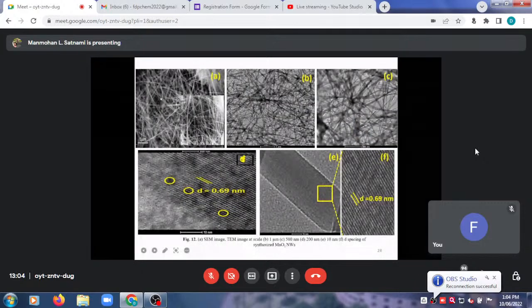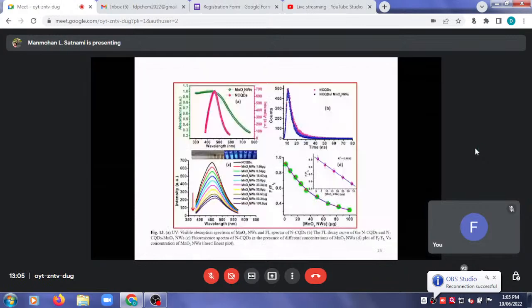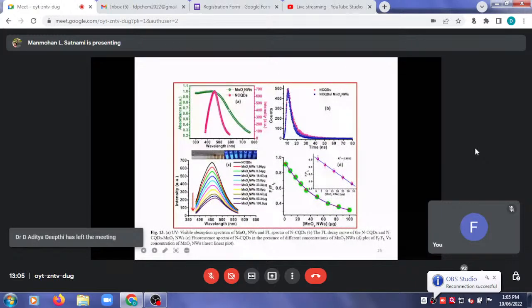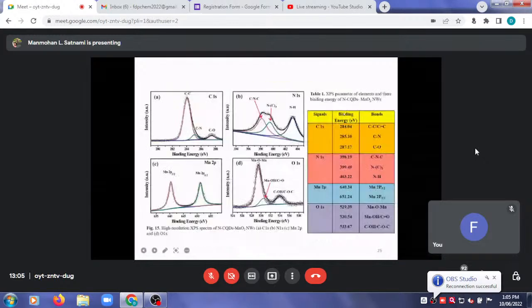This is TEM, and this is once again a TEM image of your MnO2 nanowire. From here you can see the fringes, the difference between two layers, which is 0.69 nanometer, and therefore the MnO2 nanowire we prepared is pure. These all are the same. So this I have already discussed. Using this phenomenon, we calculated the FRET efficiency.